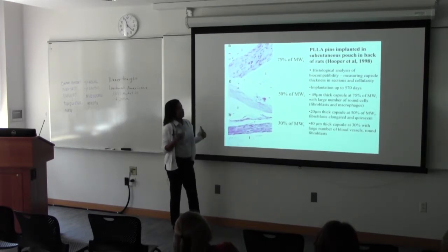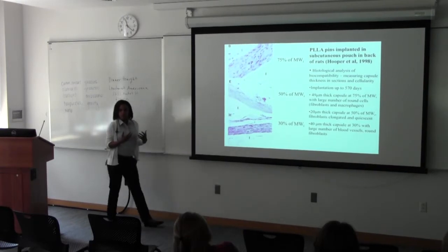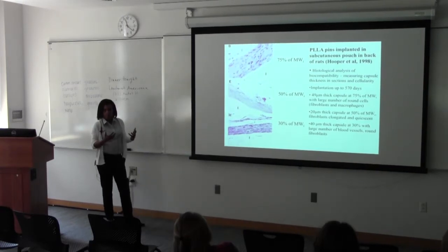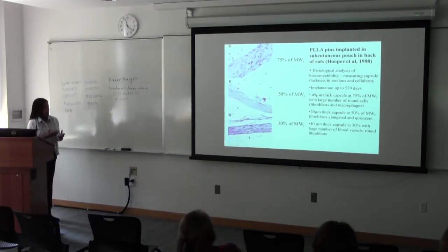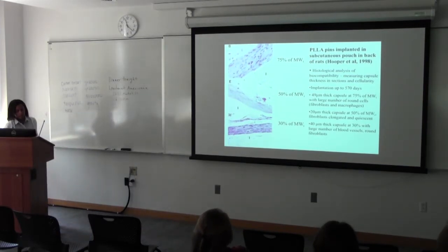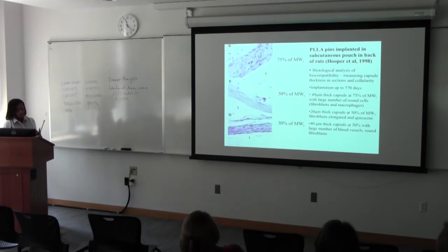You've got a lot of fibroblasts and macrophages just hanging around that material, not really forming tissue up against it. You want bone up against it in this case, but you're not really getting that, right? Because you're getting a constant dump of lactic acid in the environment. So that's always been the challenge with that material, especially in bulk form, where it's a solid implant. When it's made into scaffolding and very porous, it doesn't pose that much of a problem in terms of degradation.